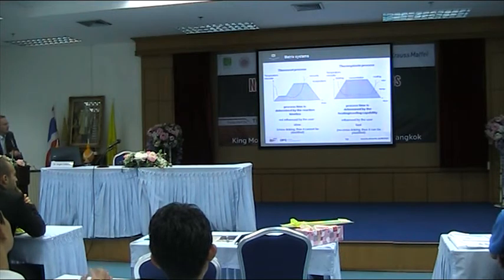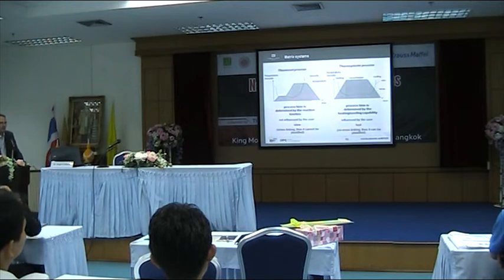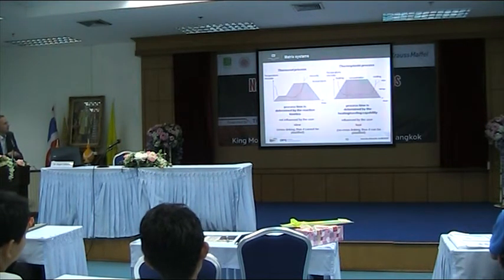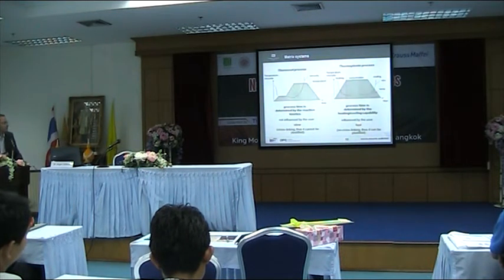With the heating, the melt viscosity goes down, but, I will show you later, not to a viscosity level like thermoset resin, which is much higher. With heating, you have a lowering of the viscosity. Then, if you have a thermoplastic prepreg, consolidation means you want, with high pressure, to get the material into the mold, or you have a thermoforming process where you consolidate the thermoplastic prepreg, and then you are actively cooling, and the viscosity increases because of the solidification process. And with thermoplastic, you have no cross-linking, so you do not have to wait.